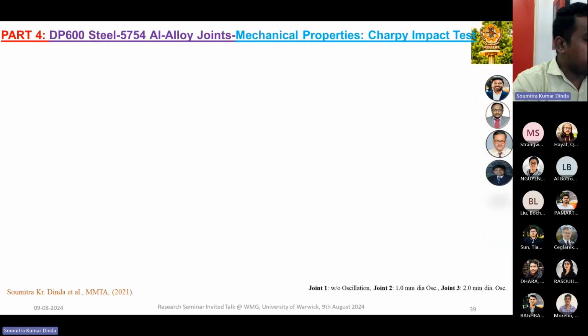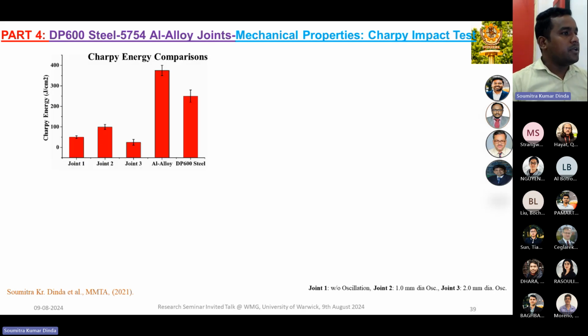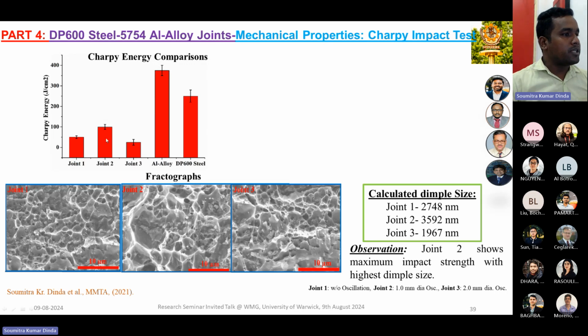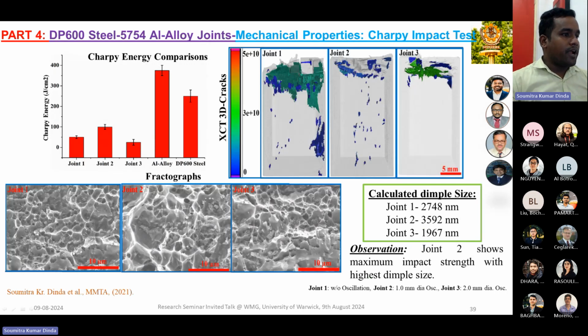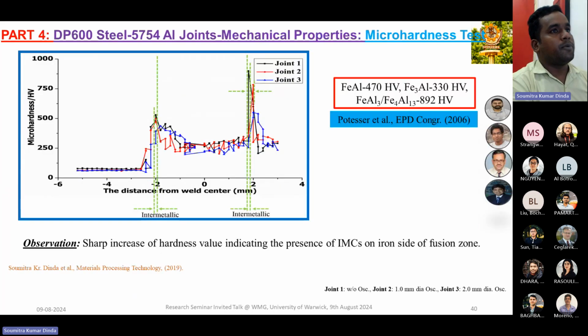Then we did the impact study, using the Charpy impact test. Again, we get a similar trend, that joint 2 gets the best, or maximum, energy. We did the fractograph analysis again and calculated the dimple size, and also did the tomography study to observe the crack nature, that is the crack formed due to the Charpy impact experiment.